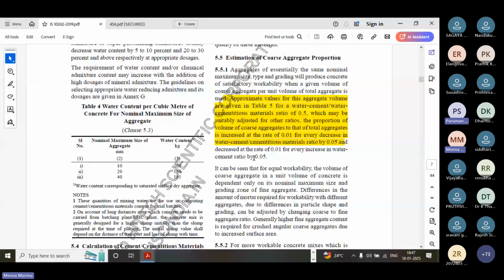So now our water-cement ratio is 0.42. From 0.5 it is lesser by 0.08. So for 0.08, by interpolation, we can increase the volume of coarse aggregate from 0.62, as per Zone 2. Here we can increase approximately 0.02. So 0.62 plus 0.02 is 0.64, our volume of coarse aggregate.